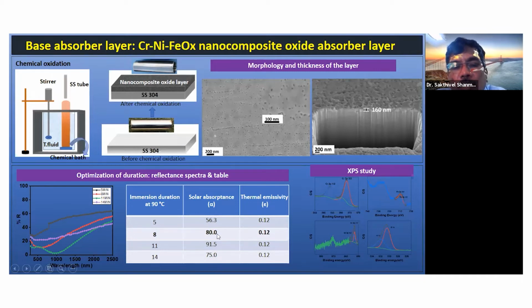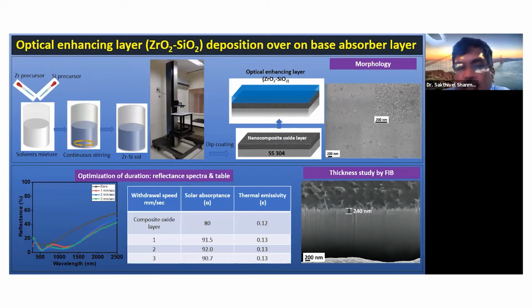In this case, we used the 80% optical absorption layer, which shows very good thermal stability as well as mechanical and corrosion stability. After that, for this application, the coating must have more than 90%, and for that reason we applied another nano-composite layer using a dip coating process. The only thing is, it is a potential technology, so that technology should have high scalability.